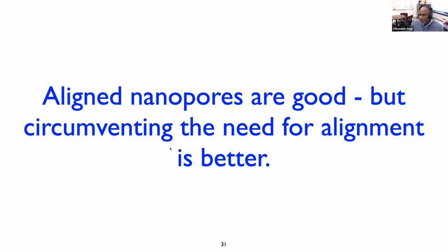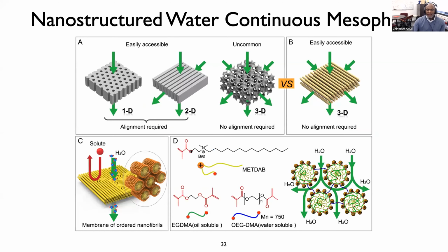And aligned nanopores are good, but if you can circumvent the need for alignment, that would be even better, I would argue. And so what we've been working on in recent years is a system that involves filtration, that involves selective transport, not by flow through a cylindrical pore, as we've historically done, or by flow through a lamellar or sheet-like slit, which also requires alignment. And it's not by flow through a bicontinuous cubic morphology, for example, as you can find with the gyroid systems, where you don't need alignment, but where the pore stability of the phase makes it difficult to work with.